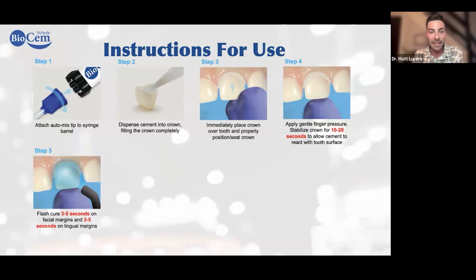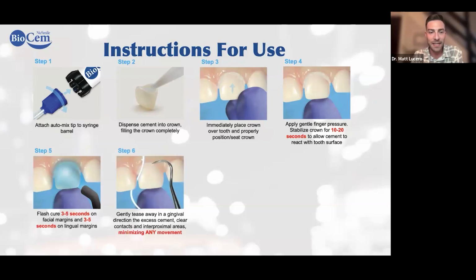Then we'll tack cure it in place. That'll kind of rubberize the material, allow us to clean it up. And depending on your curing light, it'll be 3 to 5 seconds or so. If you have a Valo, a little bit less. If you have a little bit weaker light, maybe a little bit more. At this stage, we'll clean up our excess, like I mentioned. You want to hold that crown in place because we're not fully polymerized. If we move the crown, we're going to break those polymers that we've already created, and then they're not going to be able to repolymerize. You got to hold everything in place at this stage.